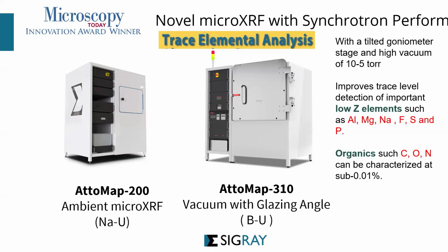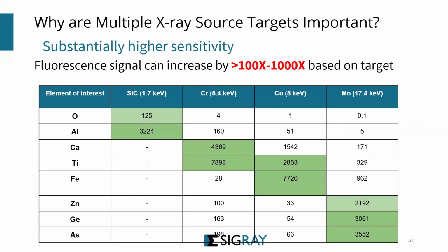0.01%. In contrast, what is the concentration that you must have to detect an element under your SEM EDS? You need at least 1% before they can be detected. So these two allow you to not only look at sub-ppm, but you can go all the way down to your organics. What makes it possible for us to detect all these things so well is the ability to shift energy according to what we want to analyze.